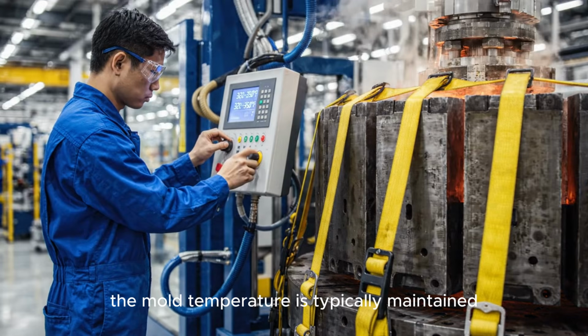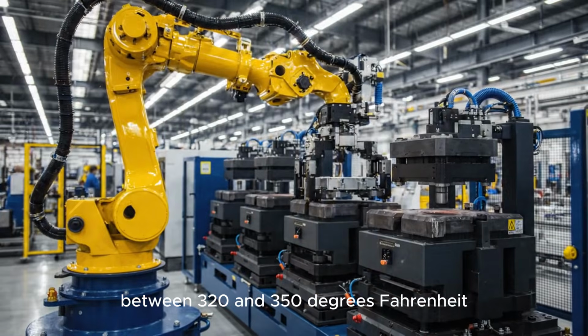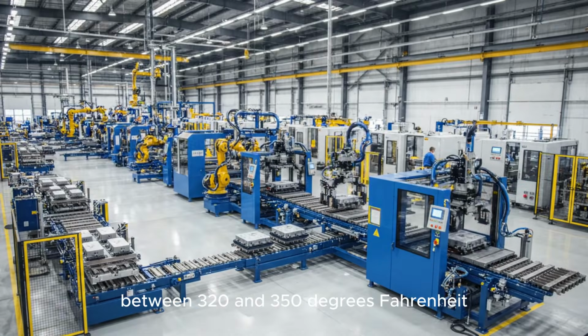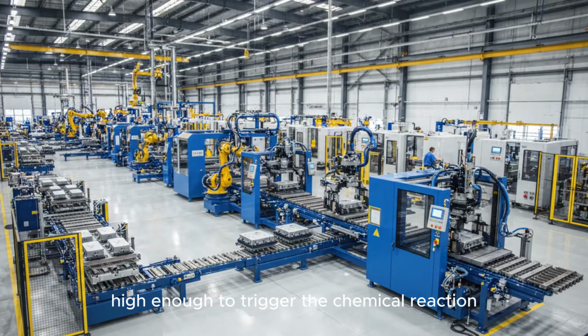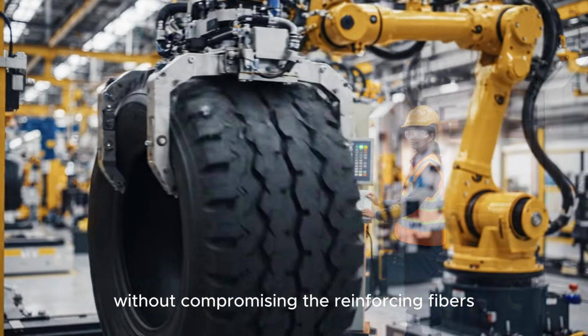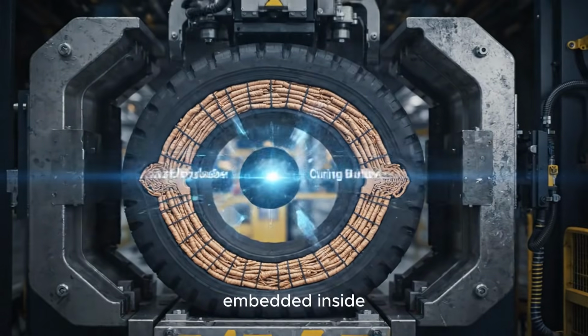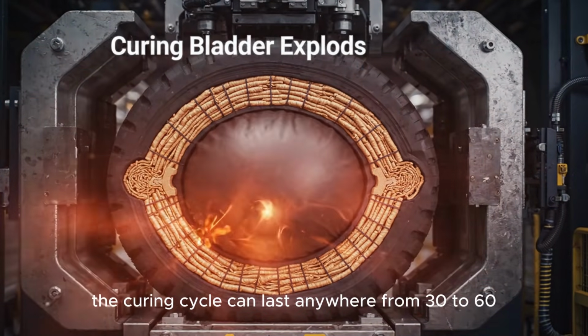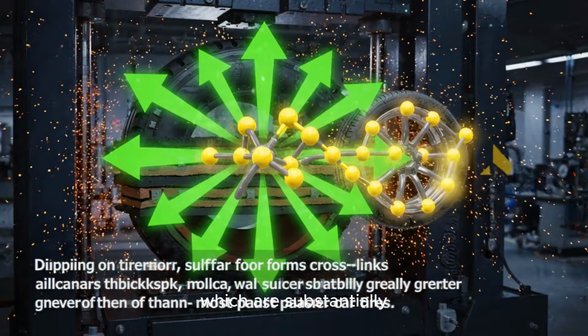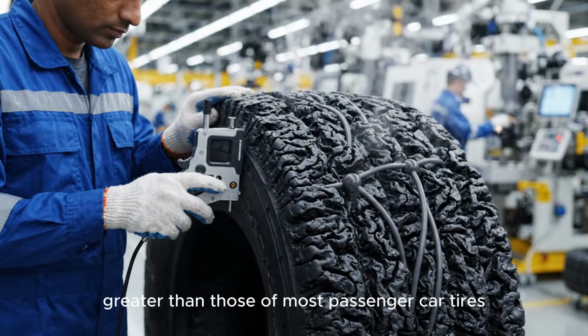The mold temperature is typically maintained between 320 and 350 degrees Fahrenheit, high enough to trigger the chemical reaction, without compromising the reinforcing fibers embedded inside. The curing cycle can last anywhere from 30 to 60 minutes, depending on tire size and carcass thickness, which are substantially greater than those of most passenger car tires.